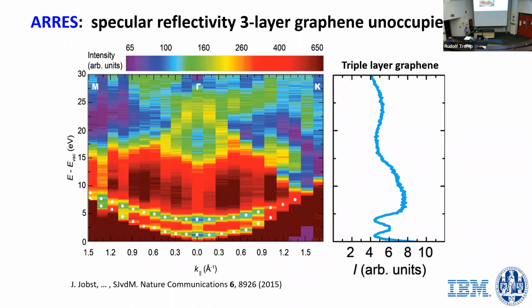It turns out that this curvature corresponds to the mass of the electron being about 1 electron mass, very close. Then we see a large red area. Red means high reflectivity, which means that we have a big band gap here. The electrons cannot go into the solid there. And then at higher energy, we see different bands develop. And it's known that graphite, for instance, does have a big band gap about 10 eV above the vacuum level.